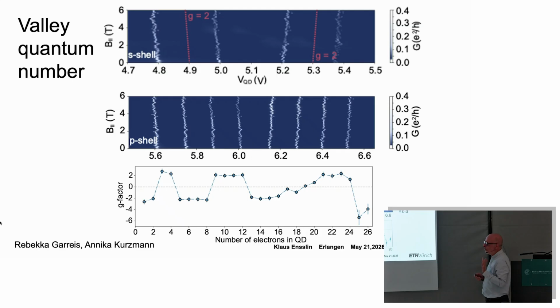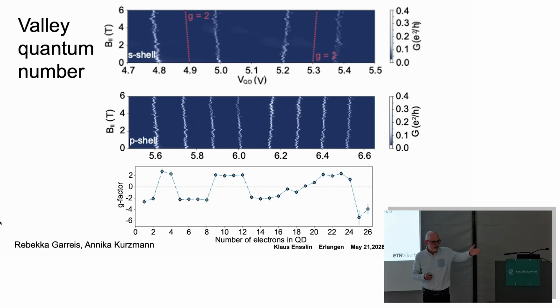Now let's see how we fill these states. So what I show you here is again the gate voltage axis. That's energy in our system. That's conductance, the color plot. And the vertical axis is an in-plane magnetic field. So it's a magnetic field that's oriented in the plane of the graphene. So it only couples to degrees of freedom that couple to in-plane fields. All the orbital degrees of freedom, and K and K prime are orbital degrees of freedom, they don't couple to an in-plane magnetic field. So it's only the spin that is left.